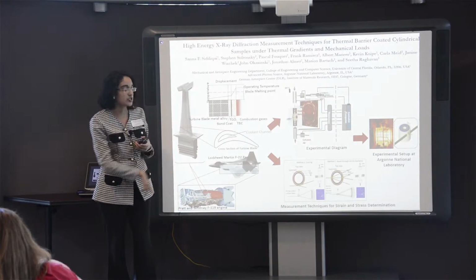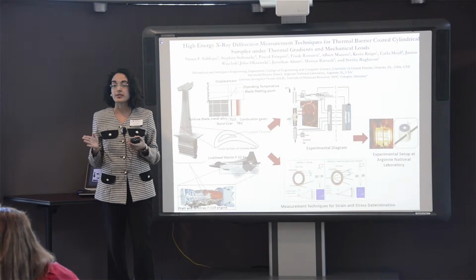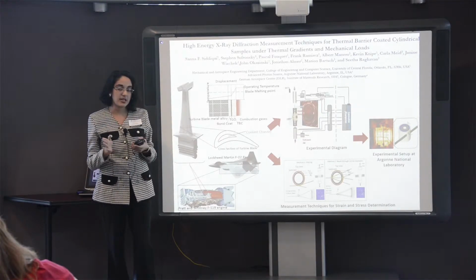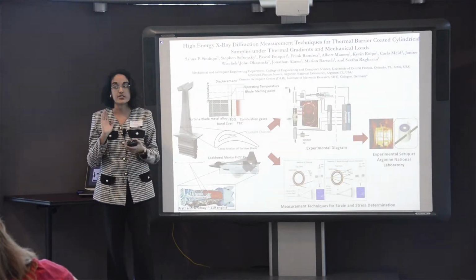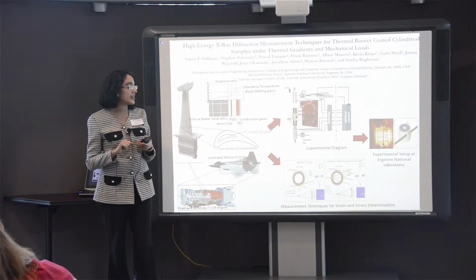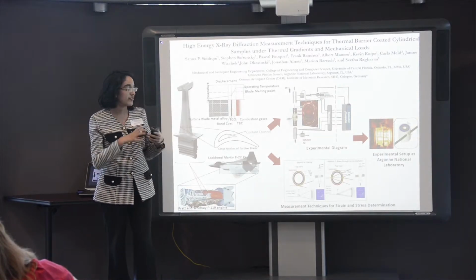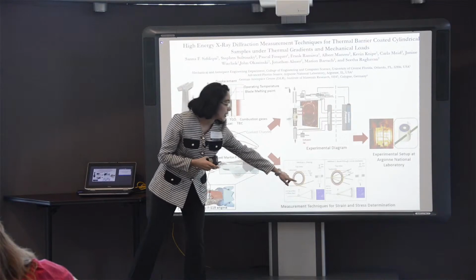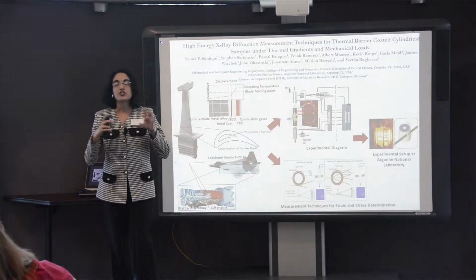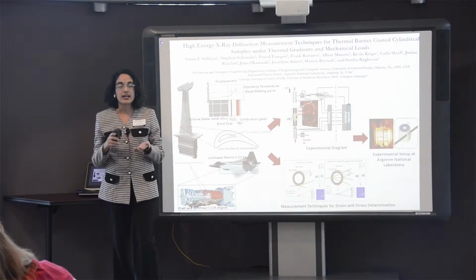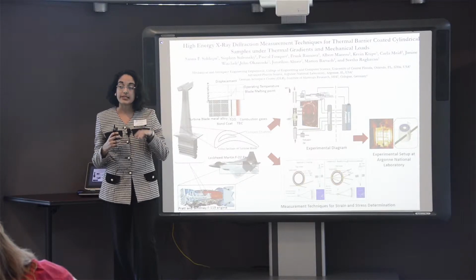The first one is grazing, where you pass the X-ray beam through the side of the sample, and the second is through center, where you pass the X-ray beam through the center of the sample, and you're able to capture diffraction patterns or rings, which are shown on the bottom down here. Basically, each diffraction ring represents the atomic plane or spacing in each particular layer.